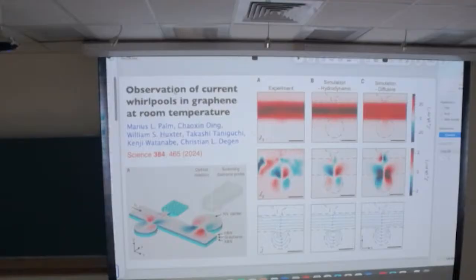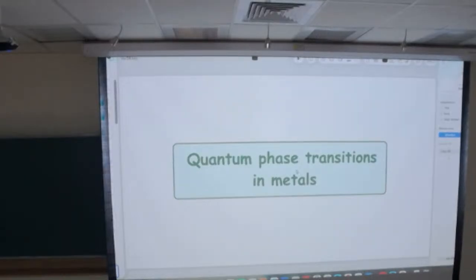All right, so I would say that this particular Dirac semi-metal is reasonably well understood. We can do some microscopic theory, and at least on the scale of the other strange metals and so many other materials, it has a common feature that the relaxation time is Planckian, but the overall scale of the conductivity is much larger in the cuprates than over here. Here it's e squared over h, which is not such a good conductivity. All right, so let's go on to strange metals then.